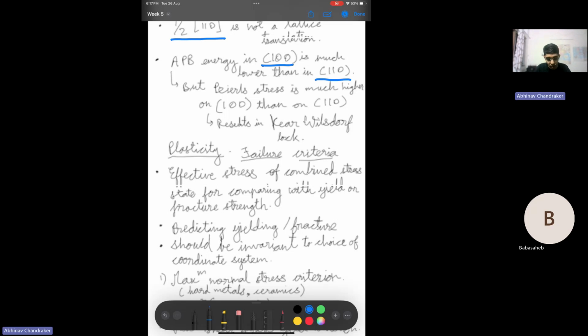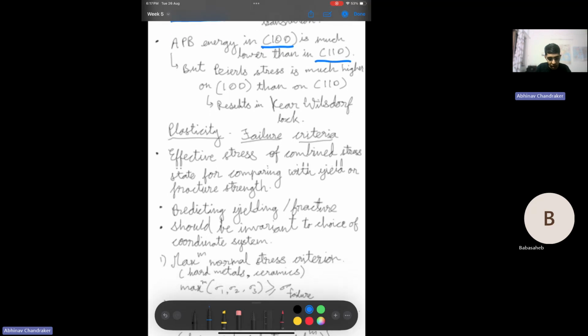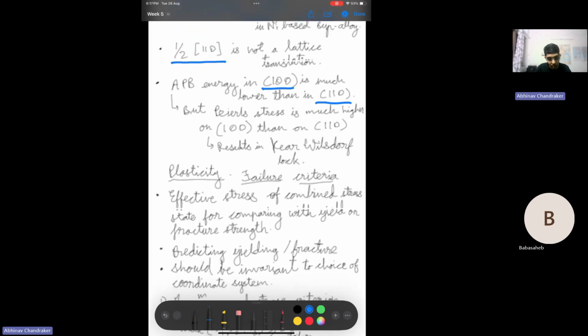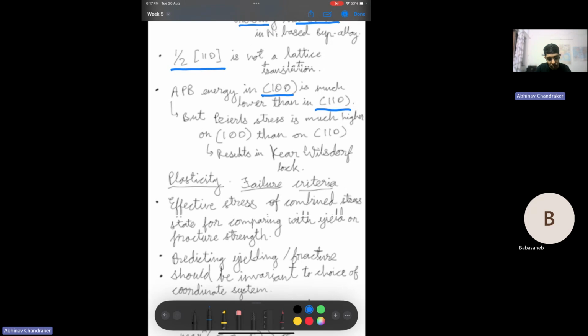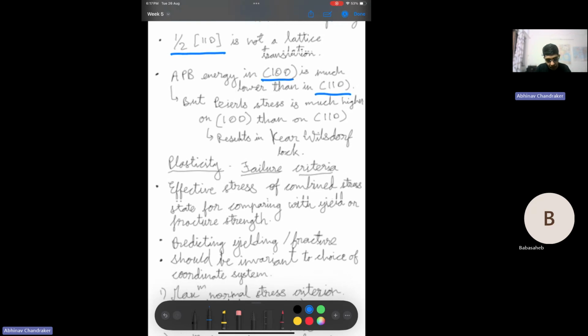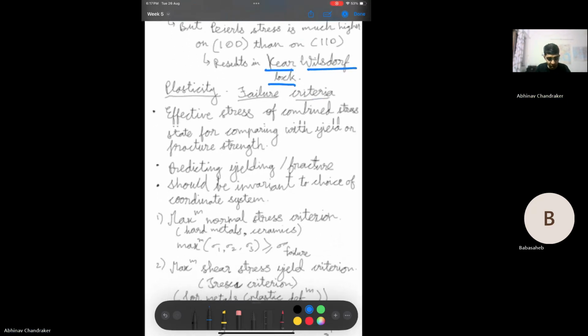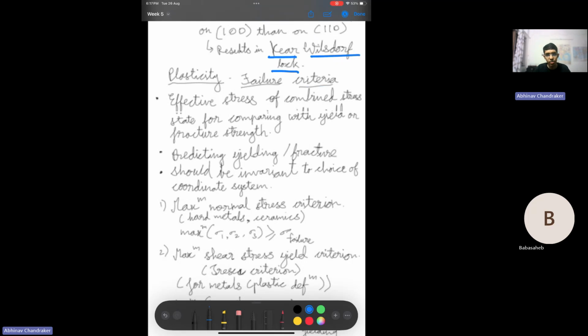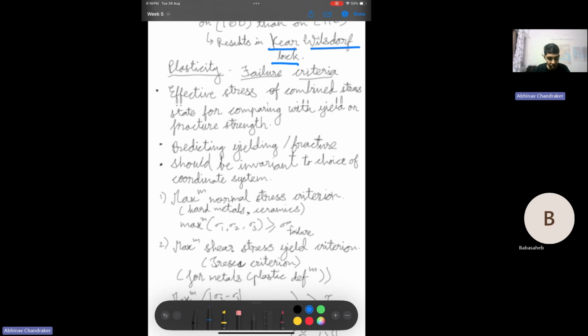As a result, due to this phenomenon, we see that a kind of lock forms, which makes it difficult for dislocations to move. Even though APBs are more favorable in 100, the mobility is lower. So Kear-Wilsdorf lock forms in such cases, and these locks can lead to strengthening and work hardening. We'll see how that happens in the subsequent points.